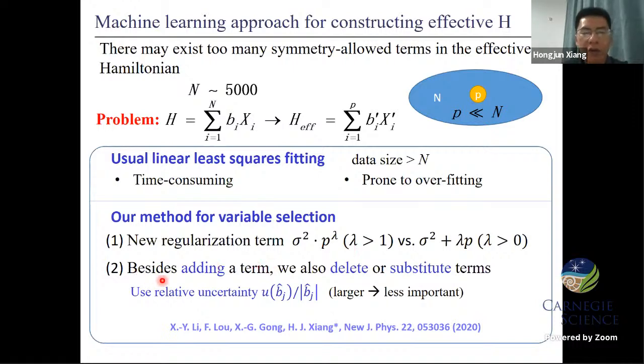Another feature of our method is this. Usually there are some methods proposed before for variable selection. They usually just add terms one by one. Each time they add one important term, and then next they add the important terms from the remaining terms. But we find that that kind of process may add wrong terms. So besides adding terms, we also delete or substitute terms. In this way we can remove the unimportant terms from the already selected terms, and we think we can solve the variable selection problem.